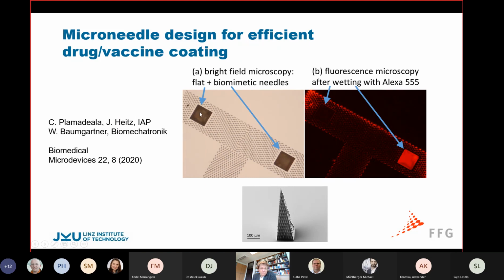And the left pyramid, there's also a pyramid here, but it has a flat surface, so it doesn't have these microstructures. And then you apply this solution with the Alexa 555, and then you see that this solution creeps up this needle, which is microstructured, but it does not creep up the needle, which just has flat surfaces.